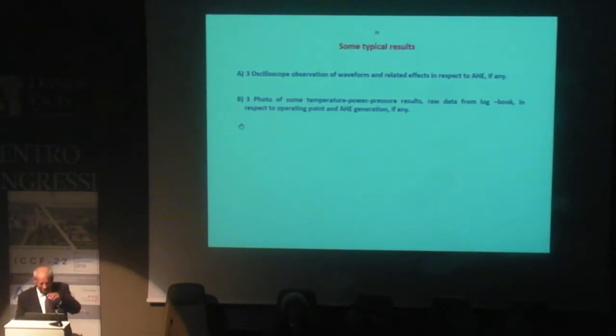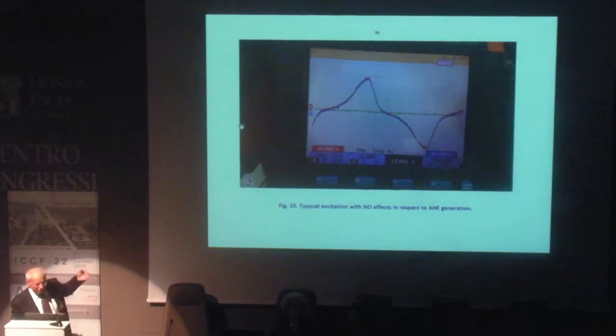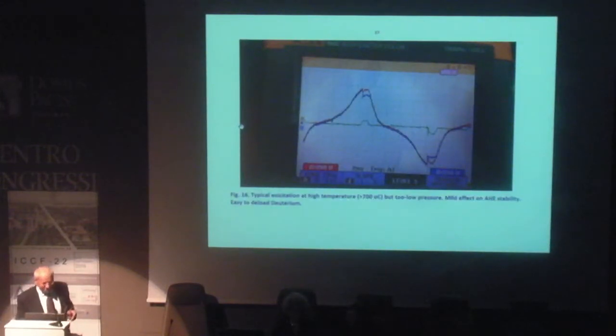Some typical results. This is what happens to the counter electrode when the pulse, even if present, is not absorbed by the active wire. So you have almost the same voltage in and out of the resistance. No effect. You give power, nothing happens. This is an intermediate regime. The temperature is high enough to have a Richardson effect, but the pressure was too low. We intentionally reduced the pressure as much as possible. So we have symmetric current, and the Richardson law means electrons and ions quite similar. There is some effect, but it was weak.